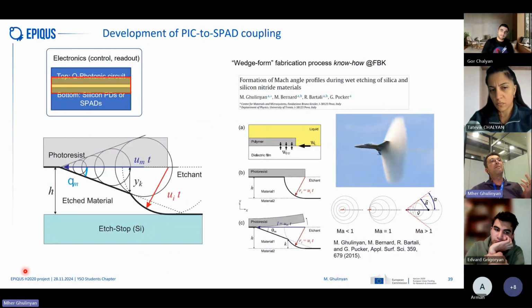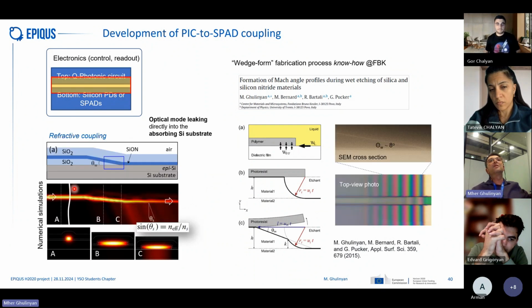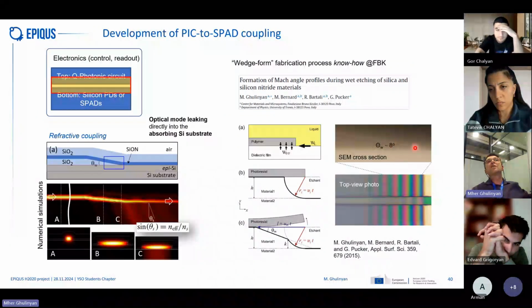The same thing is happening formally when the liquid, your acid, is penetrating under. So it is creating circular shaped etching at each new point. And all these circles, you can see how similar they are. They are sitting on the same line. And if you etch very long, they will create a very triangular shape of your surface. And this is in a cross-sectional image.